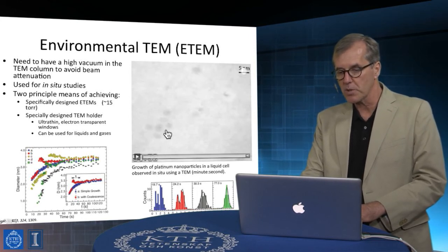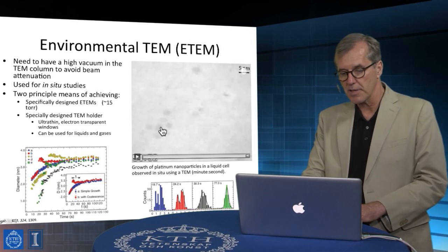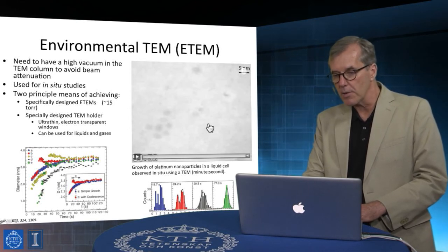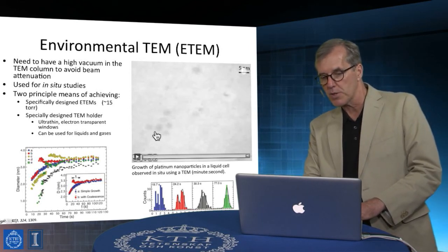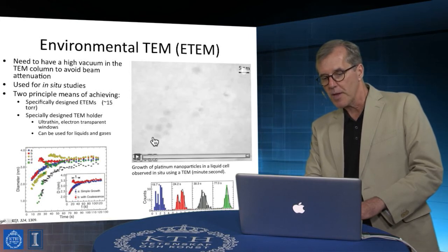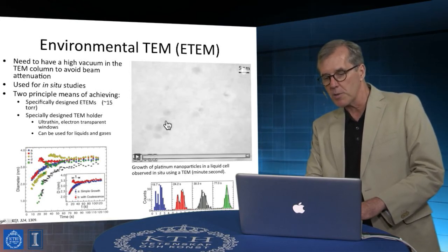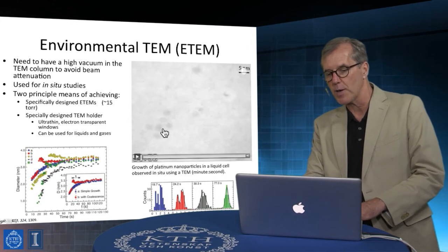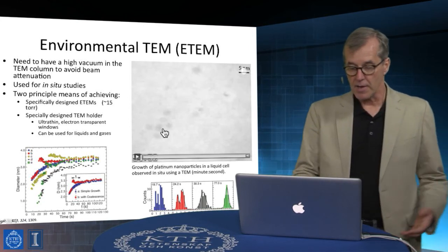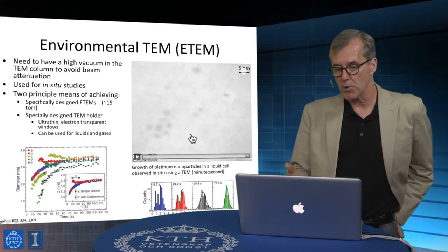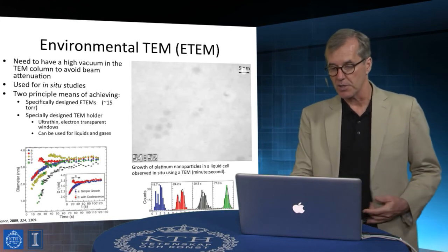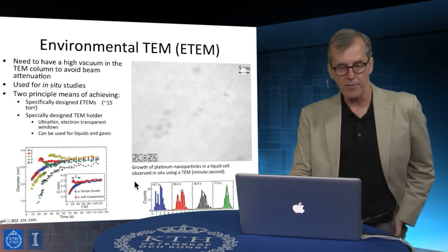These are platinum clusters of, say, a nanometer. So that's a 5 nanometer scale bar. So these are like 5 nanometer clusters, and you can see them starting to arrange themselves with hexagonal symmetry around a central core cluster, and actually following that growth pattern and self-organization in real time in a fluid environment.